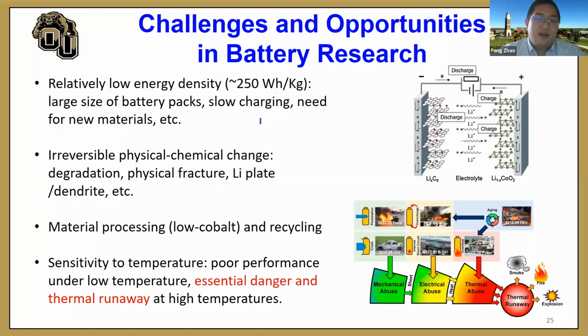The second challenge is related to battery lifetime, because there is substantial degradation during the usage of the batteries after many cycles of charging and discharging. There can even be physical fractures within the battery. There can be local lithium plating and dendrites formed, which can cause danger and hurt the battery. The third challenge is that there is a substantial need for low cobalt materials, and also a strong need for green recycling methodologies for batteries after they cannot function.